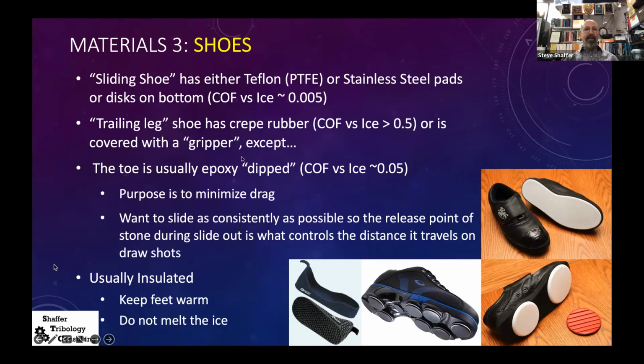And the other thing with the shoe is you can see here it's dipped in epoxy, and that gives you also a low coefficient of friction, so it's not dragging. If you're not good enough to keep your toe off the ground, it's hard enough to keep your knee off the ground. You want to minimize the drag so that you can slide as consistently as possible and as far as possible, so that when you release the stone during your slide, and you're always slowing down, the point at which you release the stone is what controls the distance it travels on draw shots.